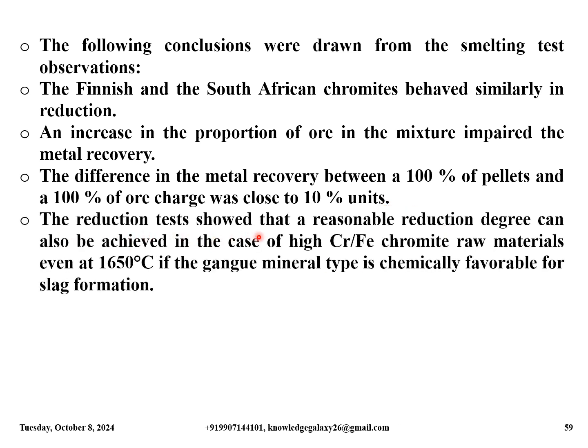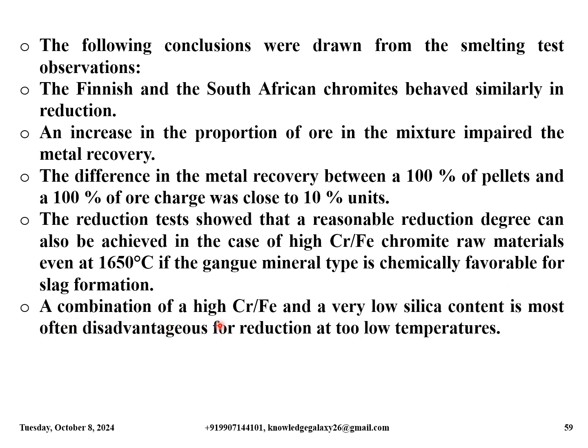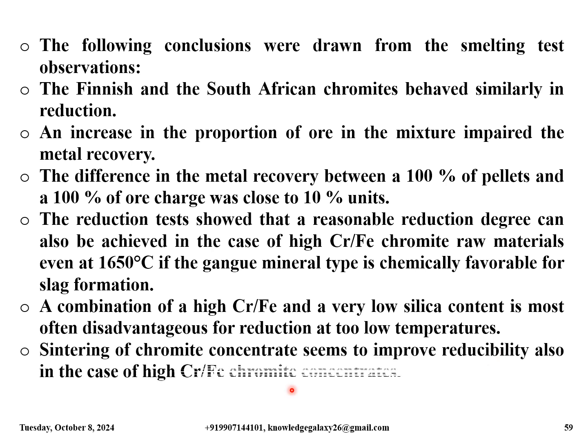The reduction tests showed that a reasonable reduction degree can also be achieved in the case of high Cr/Fe ratio chromite raw materials, even at 1650 degrees Celsius, if the gangue mineral type is chemically favorable for the slag formation. A combination of a high Cr/Fe ratio and a very low silica content is most often disadvantageous for reduction at too low temperatures. Sintering of chromite concentrate seems to improve reducibility also in the case of high Cr/Fe chromite concentrates.